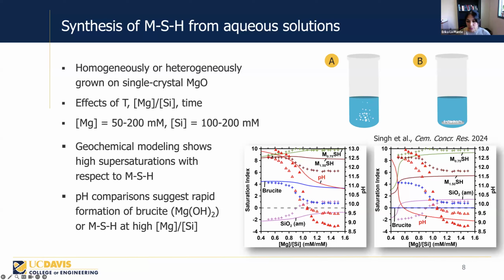We see a good correspondence between the measured values and the modeled values at low magnesium to silicon ratios. However, at high magnesium silicon ratios, we see a divergence. It's evident from the pH. So we did another calculation in which we assume equilibrium with respect to brucite. And then we can see that at high magnesium silicon ratios, we get a much better match between the measured and the calculated pH. So this modeling suggests that there's a rapid formation of brucite or MSH. So the precipitation of MSH would have the same effect at high magnesium to silicon ratios.